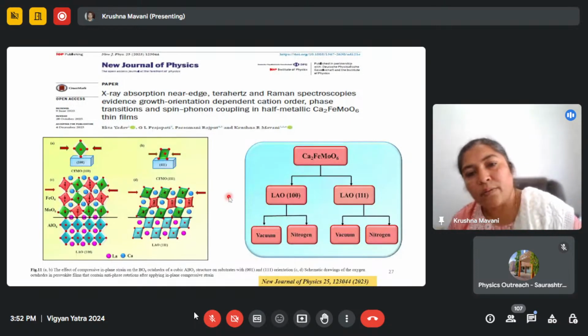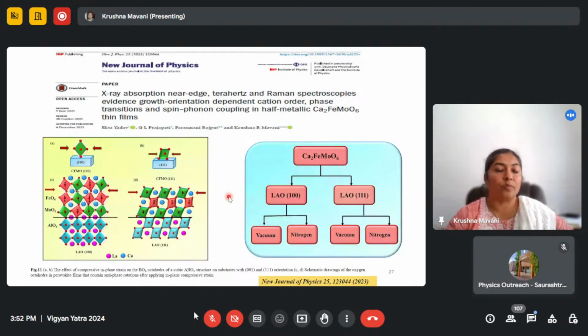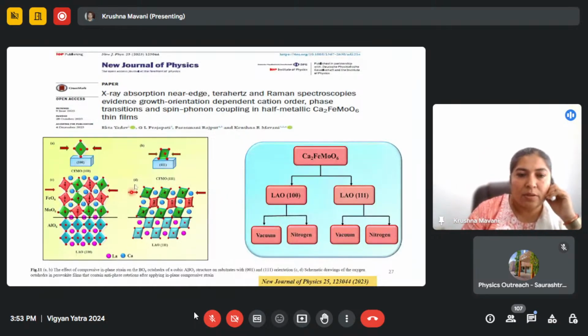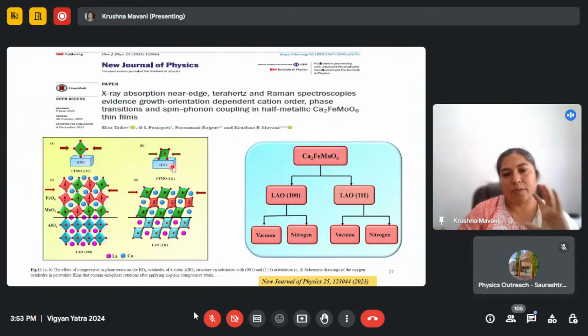And also we have another feature added here in addition to vacuum. If you choose your crystal very wisely, 100 oriented or 111 oriented, depending on that you can also control your cation order, and as you control the cation order, the half metallicity is intact, and you can have more and more spin polarization in this material. That alignment is possible when you have 111 crystallographic orientation beneath the thin film.